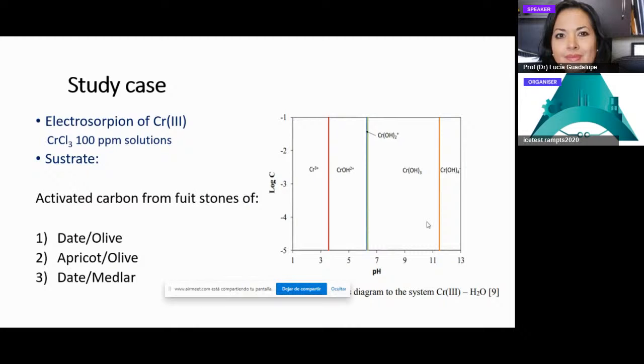In this case, I'm going to show some results about the characterization of electrodes using activated carbon to check the potential of this material. We have worked with chromium-3. We have one solution of chromium chloride at this concentration, and we have used activated carbon from natural stones from fruits and some mixes of that. This was the mix, made from stones, and then I have put here a diagram about the species of chromium.